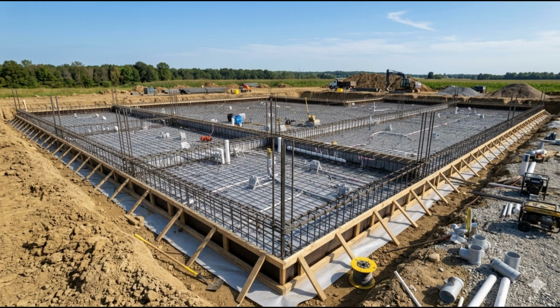Gerald specified a semi-rigid polyurethane joint sealant, applied to the cleaned and primed joint to a minimum depth of 25 mm and a width matching the joint width. The semi-rigid formulation was preferred over a flexible sealant for an industrial floor because it provided support to the joint areas under trafficking, reducing the risk of areas chipping.